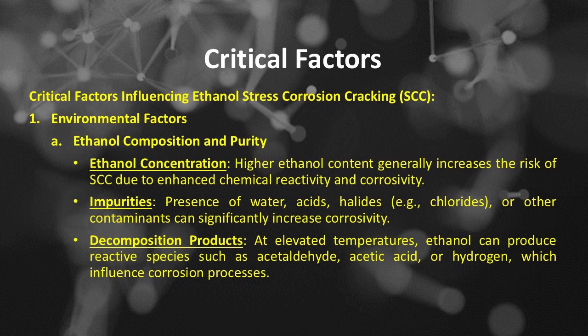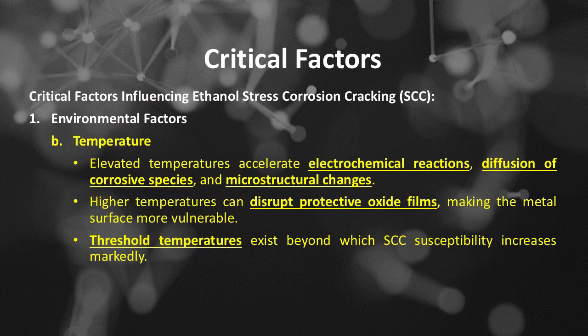Critical factors influencing ethanol stress corrosion cracking, or SCC, include: number 1 is environmental factors, which include number A, ethanol composition and purity. Ethanol concentration: higher ethanol content generally increases the risk of SCC due to enhanced chemical reactivity and corrosivity. Impurities: presence of water, acids, halides such as chlorides, or other contaminants can significantly increase corrosivity. Decomposition products: at elevated temperatures, ethanol can produce reactive species such as acetaldehyde, acetic acid, or hydrogen, which influence corrosion processes.